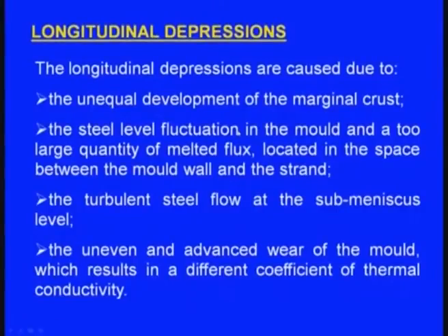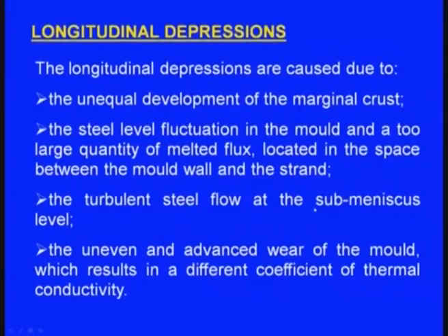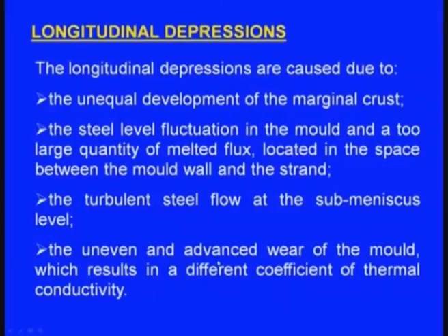Next one, longitudinal depressions. So, this is another defect. The longitudinal depressions are caused due to the following factors: the unequal development of the marginal crust. Second factor, the steel level fluctuation in the mold and a too large quantity of melted flux located in the space between the mold wall and the strand. Next factor, the turbulent steel flow at the submeniscus level, and the next factor is the uneven and advanced wear of the mold, which results in a different coefficient of thermal conductivity.